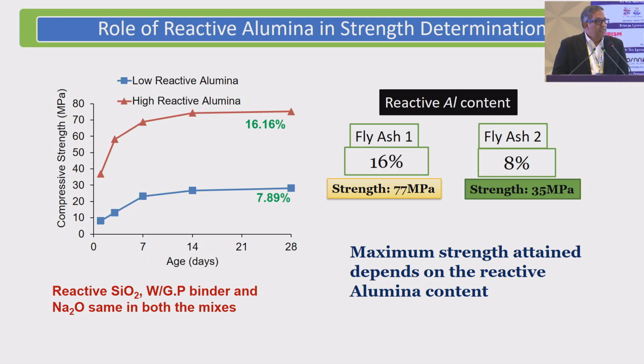Just the last slide. What determines the strength in the geopolymer system is the alumina that comes from the fly ash. So we selected two fly ashes with very different reactive alumina in them. And you see that the strengths that we get, even using the optimal ratios with the activators, are night and day. The one which had the higher alumina content gave us much higher strength. The one with the lower alumina content gave us much lower strength. So with this, we can actually formulate idealized mixtures which are based on the composition of the fly ash, where the fly ash is used effectively, utilizing all the reactive species in the material.